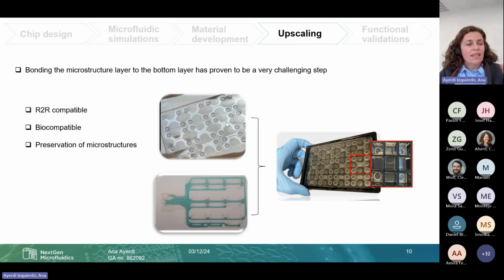Once both layers were manufactured, the upscaling of the chip was addressed. Bonding the microstructure layer to the bottom layer has proven to be a very challenging step. The requirements that this bonding should meet were that it should be roll-to-roll compatible, meaning the bonding method should be compatible with a later implementation in a roll-to-roll production line; biocompatibility, because the chosen method should not affect the cultured cells in a detrimental way afterwards; and the preservation of the microstructures as critical features of this chip design.